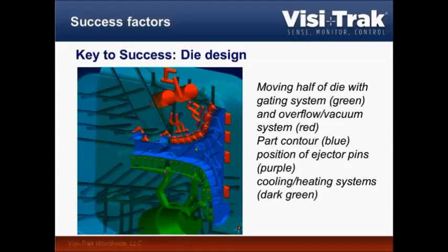Now when we talk about heating and cooling channels of these thin wall structural parts, very different to typical thick wall, let's say engine blocks or transmission cases where we shoot an awful lot of metal into this die. Here the typical wall thickness is just 2-3 millimeters, so there is very little heat coming into the die from the metal. Therefore, it's not so much about cooling the die down, it's more about heating the die to a homogeneous and to the desired temperature, and controlling that.